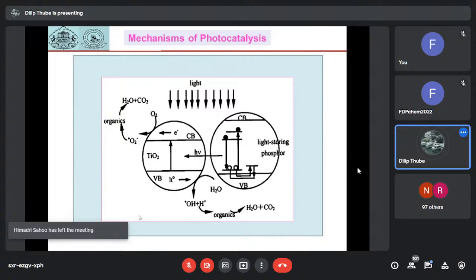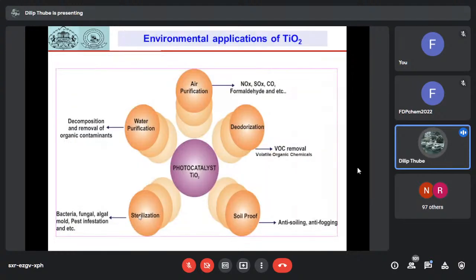And this slide shows that if you try to coat these TiO2 nanoparticles on the surface of light storing material, light storing phosphor material, these materials can be used for the days and nights together. Otherwise, if you do not have any light storing source, our materials will be useful in the sunlight only. So that limitation can be overcome by making these TiO2 nanocomposites, by supporting them with light storing materials.